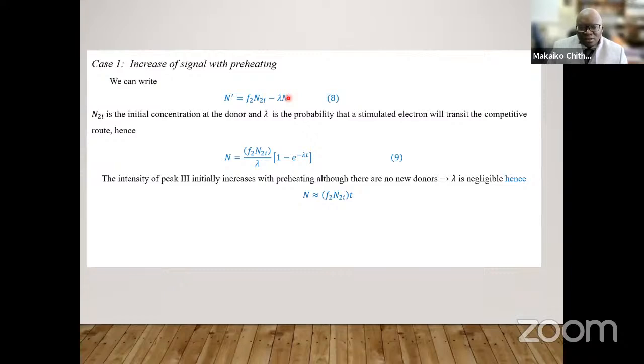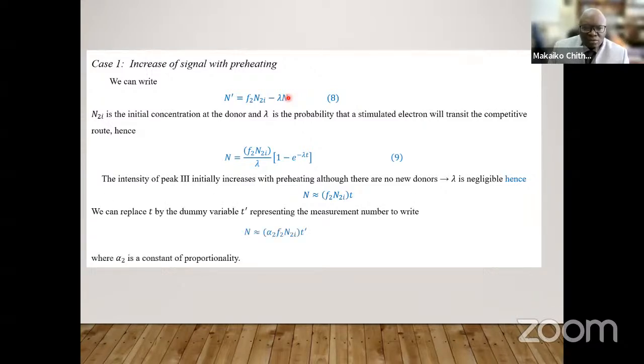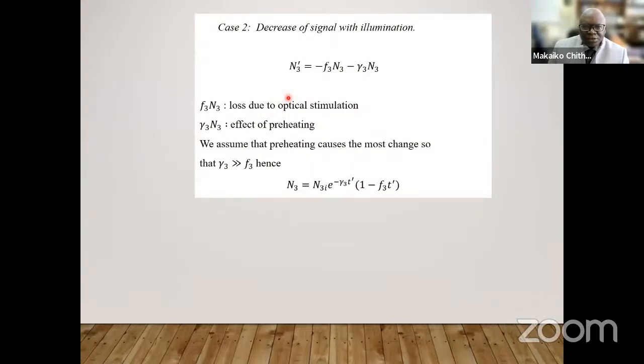But the intensity of peak 3 initially increases with preheating, although there are no new donors. So lambda must be negligible and N is just proportional to T. And for the decrease, you can express the differential equation in this way, where the first term is the loss due to optical stimulation. The second term is the loss due to preheating. But we can assume that preheating causes the most change. So if gamma 3 is greater than F3, then you simplify the solution using Taylor series, and you get this solution here for N3.